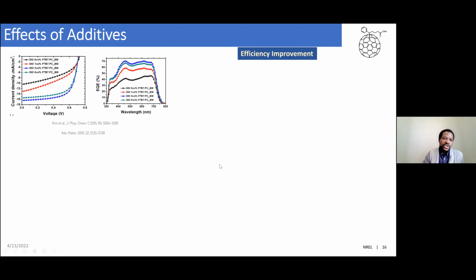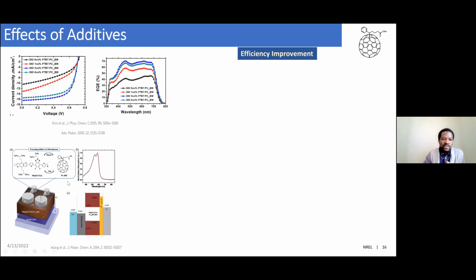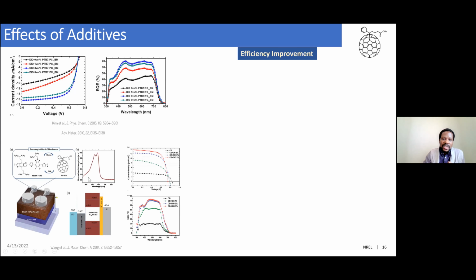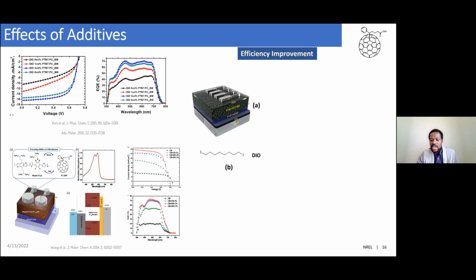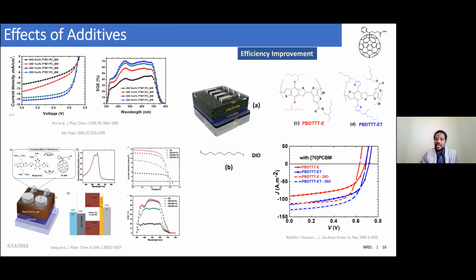And here we can see from literature, well published in the past, that when you add additives in your bulk heterojunction active layer, you are able to influence the current density by increasing it, and therefore you also increase performance. It's not just with DIO, but other additives we also use, such as chloronaphthalene or diiodohexane. And here clearly you can see that in different material combinations, they all improve the efficiency. Of course, in our case also, we decided to try that.